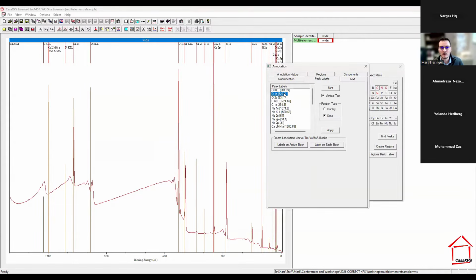And so, okay, there's oxygen. We've got an oxygen Auger, carbon, sodium. We can pick all the peaks that we see are present. And again, if you're using CasaXPS, we have some good information on my website that you can follow along and go through and do this kind of thing step by step.